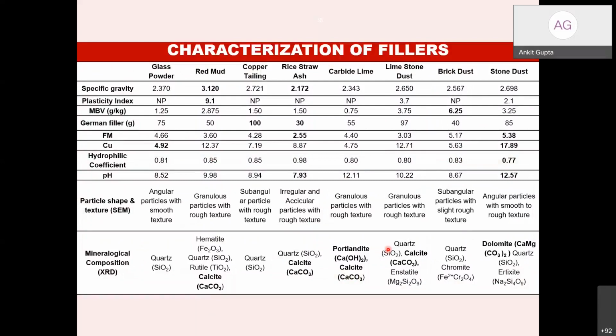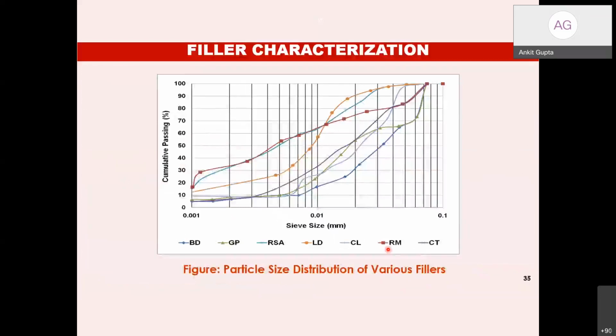Whereas the cement, the brick dust, the carbide lime, and the glass powder were the coarsest fillers among all the fillers which we have tested. Even the limestone dust and the red mud were found to be well graded. Okay, if you see the red mud and the limestone dust, these are among the well graded fillers. They have the highest CU values also. Whereas the cement, the carbide lime, and the glass powder were found to be uniformly graded. Okay, so one thing I just want to tell you is that material with a higher percentage of uniformly sized particles is normally difficult to compact properly in the field.